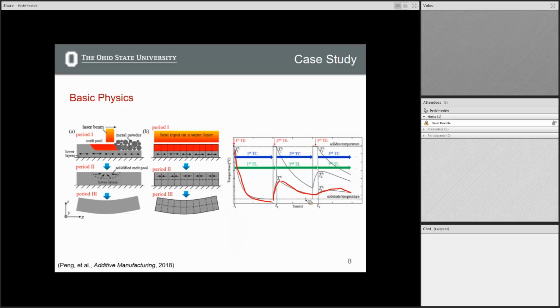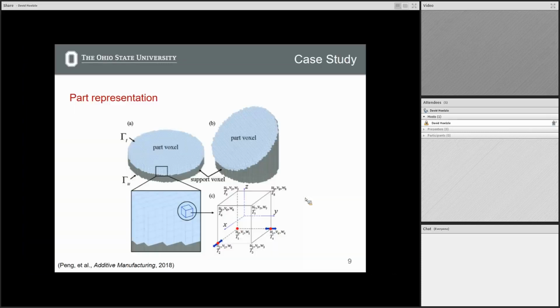So that's the basic idea of what's going on here from kind of a 1,000-foot view. We did finite element methods. This is just showing the artifacts we looked at. We were using cuboidal elements for some very practical reasons. This is pretty efficient in terms of making sure your top surface is smooth, and you can also build up multiple layers, as opposed to the more complex finite element meshes, which would have jagged interfaces at these layers as you go up.